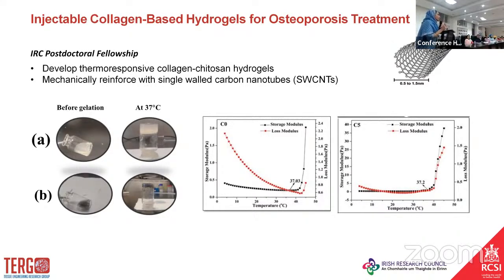a mechanical filler, because as you all know from physics, single wall carbon nanotubes have high mechanical strength. We don't use pristine ones because the FDA does not approve them. If you are using any material in biomaterials, it should be approved by the FDA, and only then can you think about human implantation. So we use functionalized single wall carbon nanotubes, which were approved by the FDA. Then we prepare thermoresponsive collagen chitosan hydrogels.